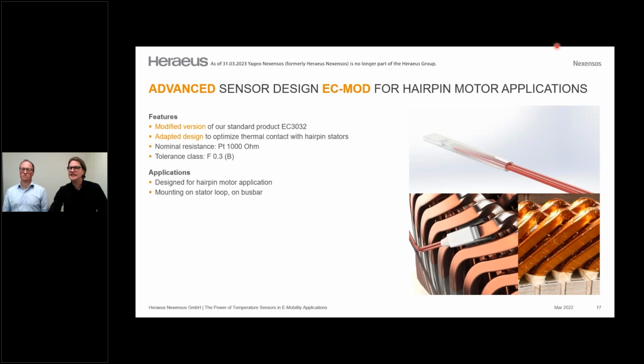Coming to the next, EC3032, but here in a modified design. We have that modified version with a flat tip. That leads to a very good connecting situation if it comes to a flat temperature sensing element. That means, if you have in mind, as shown here on the right side, that hairpin technology where not round wires are wound, here we have these flat hairpins, which look more like a bar. We are able to press our very flat sensor on top of that bar, and the heat transfer is optimized over an area, not over a line. This helps us to have really good